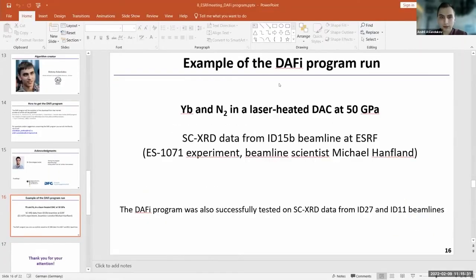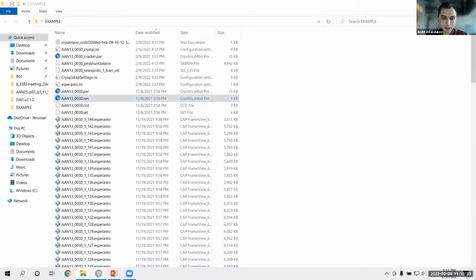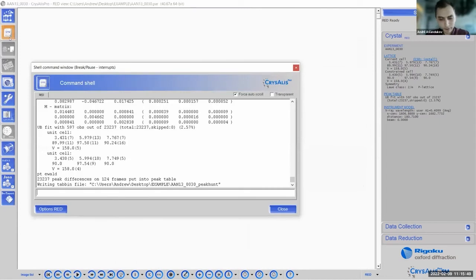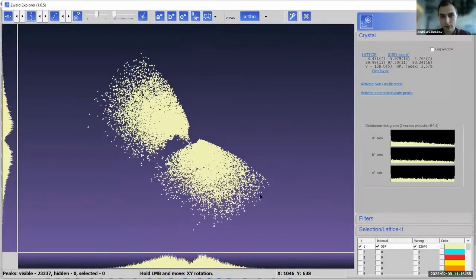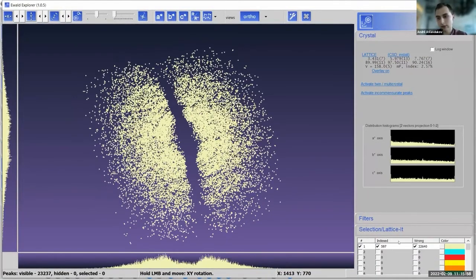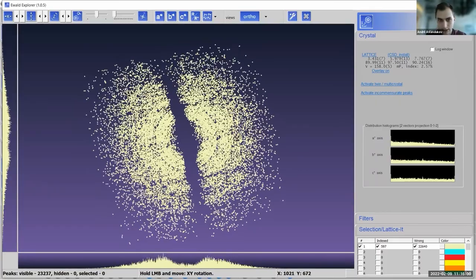So let me close the presentation, go to CrysAlis. So we collected single crystal X-ray diffraction data in plus minus 38 omega degree range. Maybe it's poorly seen here. But after peak hunting, we found almost 23,000 reflections.